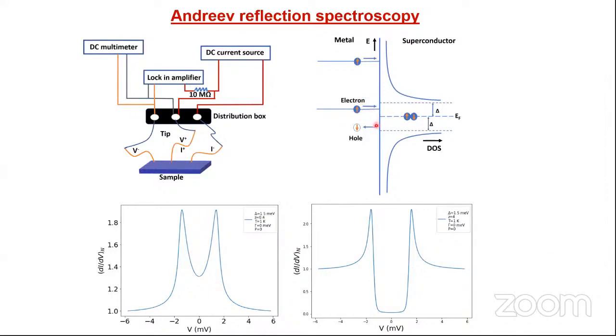This electron reflects back as a hole when the electron energy is less than the superconducting energy gap. And for charge conservation, a Cooper pair propagates inside the superconductor. And this interface can be modeled as a delta function potential barrier. When the barrier is not transparent, we know that if we measure dI/dV, then these peaks appear close to the superconducting energy gap. When we have a very large barrier, we have the coherence peaks as we see in STM spectroscopy. But in the metallic regime, when these peaks appear, we know that we are looking at Andreev reflection.